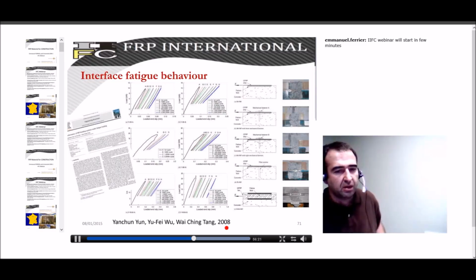I can mention, for example, this one in 2008. This is fatigue behavior of block connected by anchorage system. This is also a very interesting paper because they have tested several systems: only bonded system, a small anchor system, mesh, fibrous anchors, and also trying to bond straps onto the surface. Those authors tested all these configurations, have also observed an increase in the slip, as I mentioned first, and they also seen that there is a slight decrease.